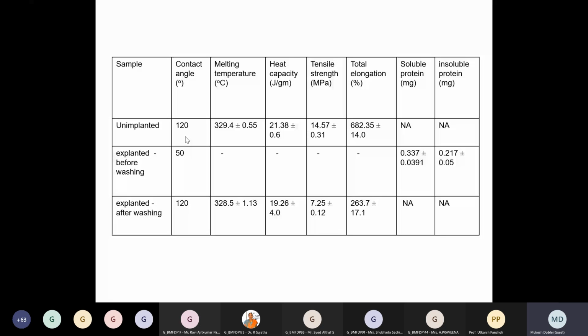As you can see, when it is explanted, because of the attachment of blood proteins and plasma proteins, it becomes very hydrophilic. It comes down to 50 degrees, but when we wash it, it goes back. Heat capacity has gone down, like I showed previously, from 21 to an average of 19. Tensile strength has gone down from 14 megapascal to 7. Although it's only blood flowing inside, because it's been there for 1.5 to 2 years, tensile strength has gone down quite a lot. Elongation has gone down from 682% to 263. That means the polymer has become stiff.